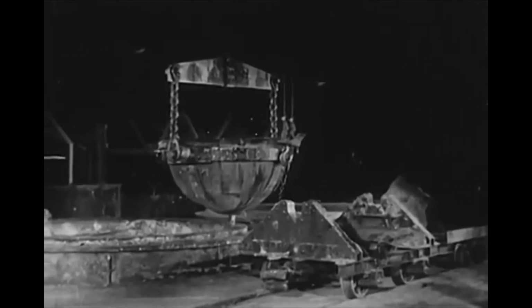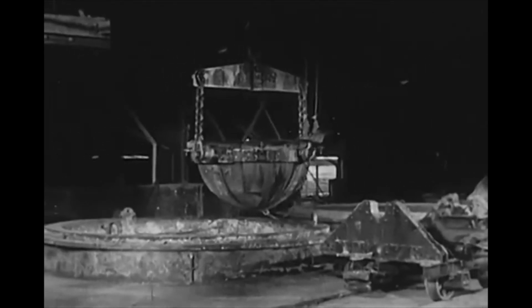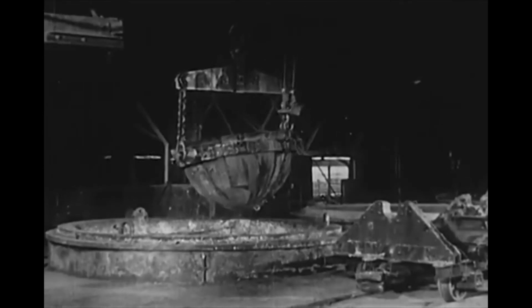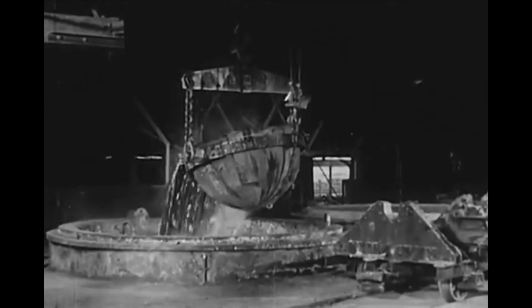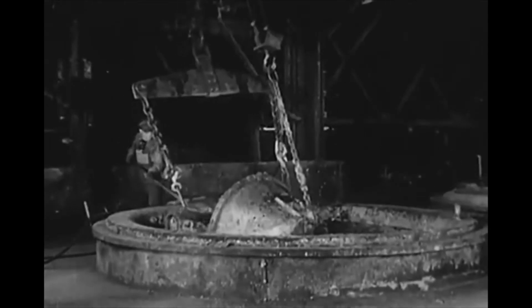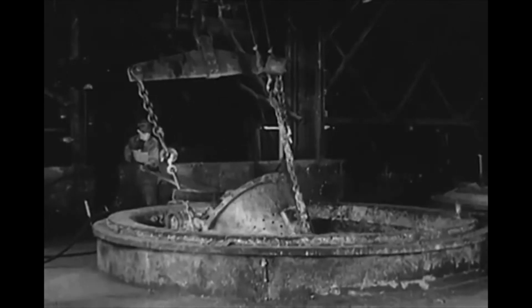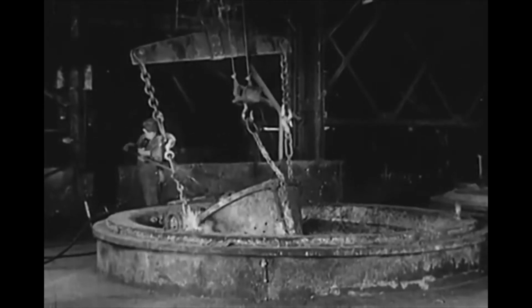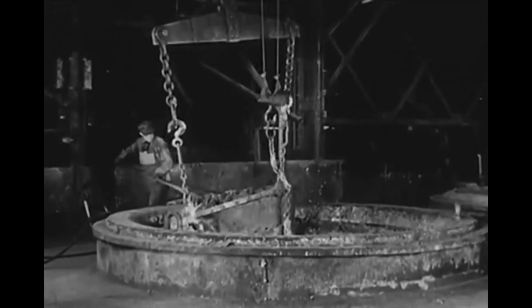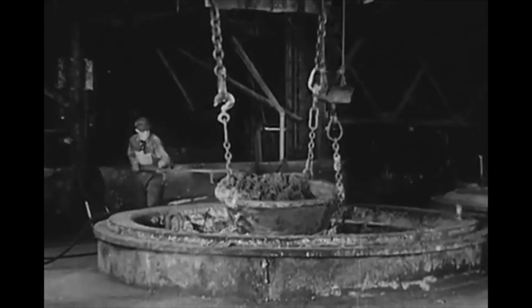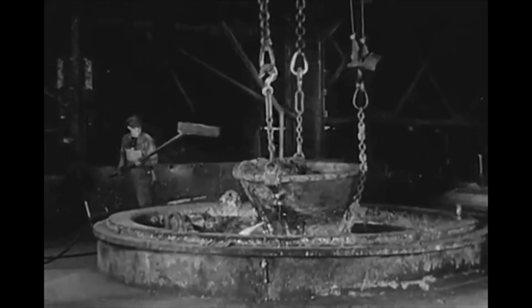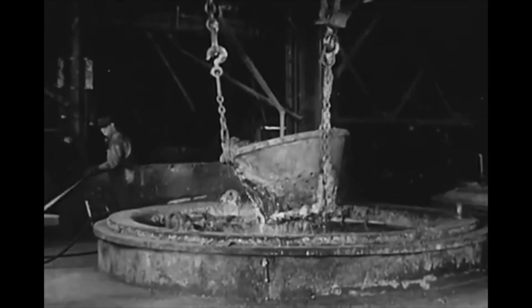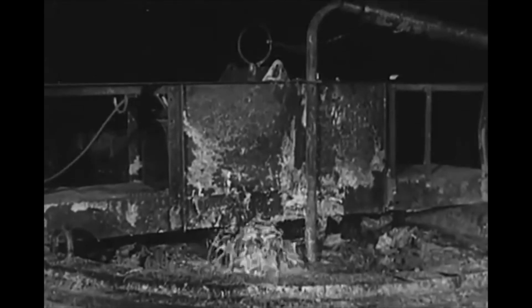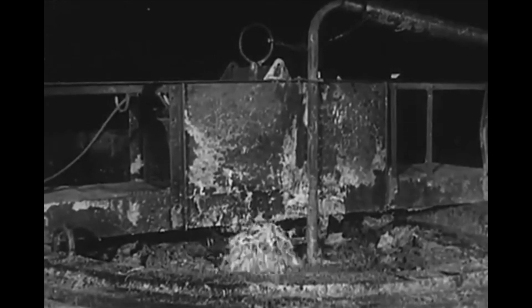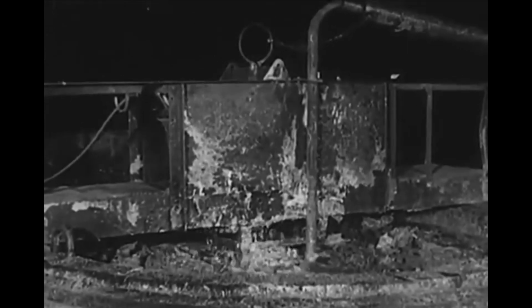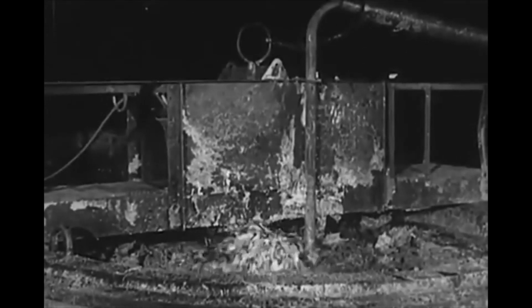The lead pot is hoisted by an electrically controlled crane, which is operated from the floor, and the metal is poured into the rough drossing kettle. A perforated dross basket with a capacity of 3.5 tons is immersed in the kettle. Skimming off the dross, the basket is hoisted by the crane and suspended above the kettle while the metallic lead drains back. A centrifugal pump is inserted under the small remaining quantity of the dross and serves to pump the metallic lead to an adjoining kettle.